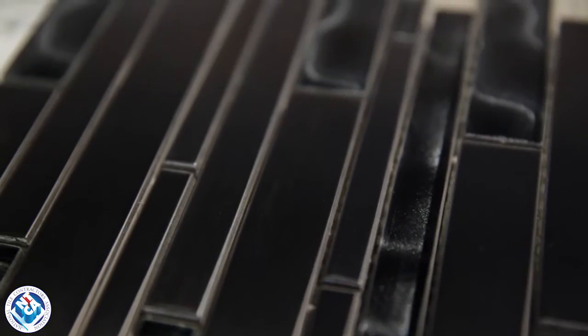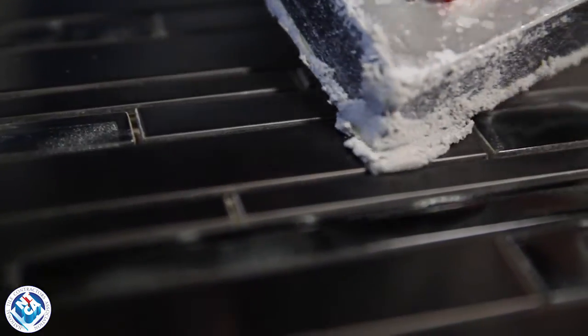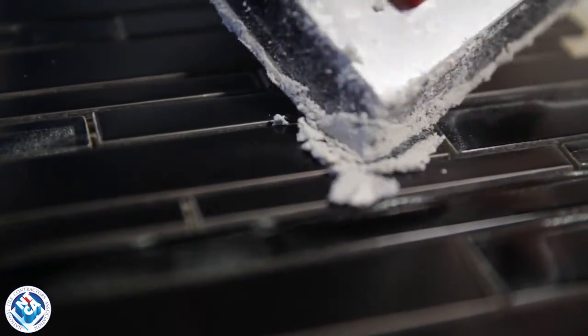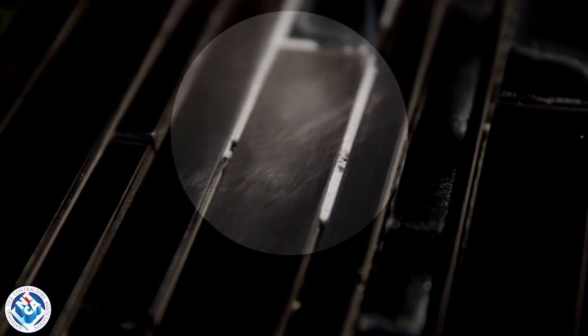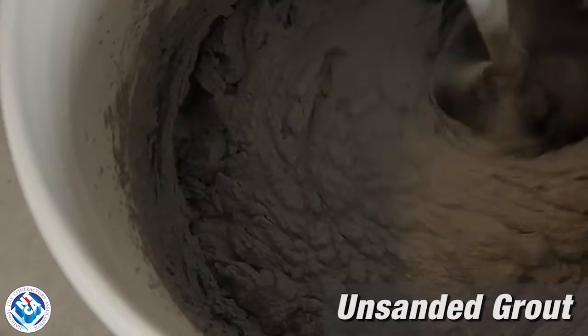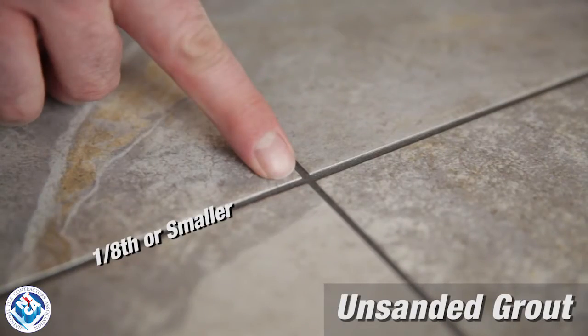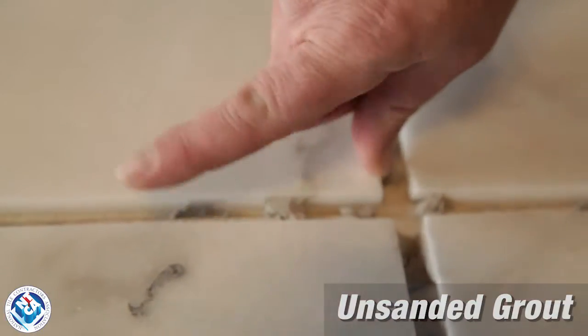If the tile is questionable, test a small area to find out if sanded grout will work with your tile. If scratching or damaging of the tile occurs, unsanded grout should be used. Unsanded grout is used when filling joints up to 1/8 inch wide. Do not use on joints larger than that because it might shrink and cause cracking because of the lack of sand, also known as aggregate, in the grout.